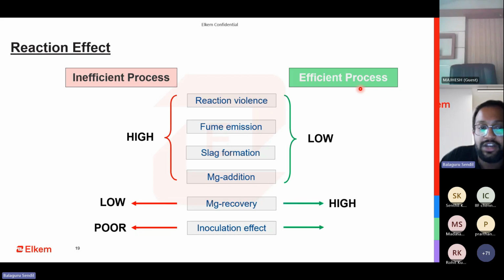If it is on the poorer side, your process is inefficient. If your magnesium recovery is above 60%, which is good, your magnesium addition will be low, your slag formation will be low, your fumes will also be low, your reaction violence will also be low. So if you're able to get all these things low, it is a much better product. It is a much better treatment process that you are having. It is always advisable to have less is better when it comes to doing ductile iron treatment.